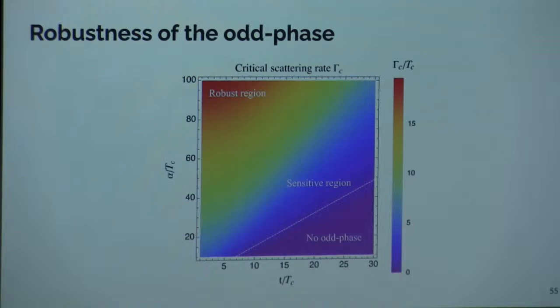The color code shows the critical scattering rate necessary to obliterate the odd phase. The even phase cannot be obliterated. The vertical axis is spin-orbit coupling, the horizontal axis is interlayer hopping, and you see that there is an appreciable region which is quite robust against impurities.